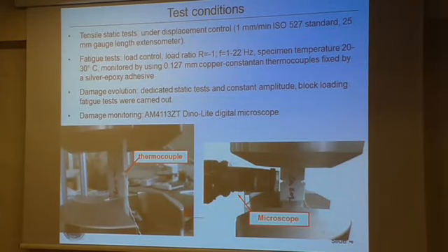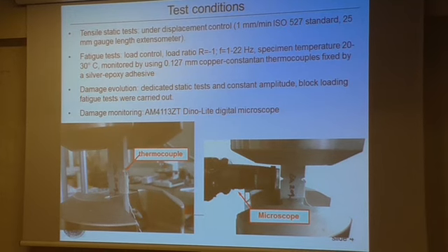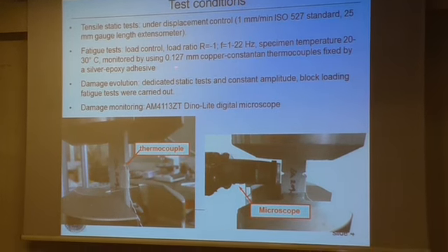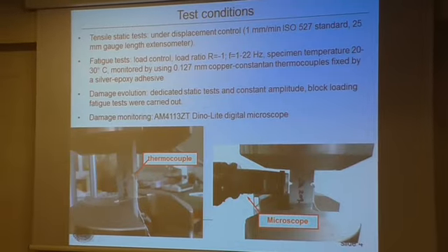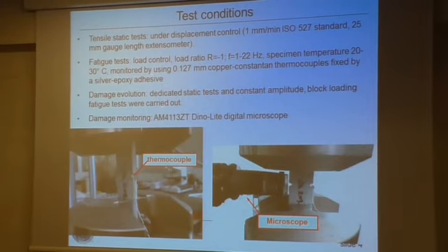Standards, fatigue tests were carried out under load control by imposing a sinusoidal waveform and with a load ratio equal to -1. Test frequencies ranged from 1 to 22 Hz, depending on the applied stress level, in order to maintain the material temperature below 30 degrees Celsius. Temperature was measured by gluing a thermocouple at the notch tip.